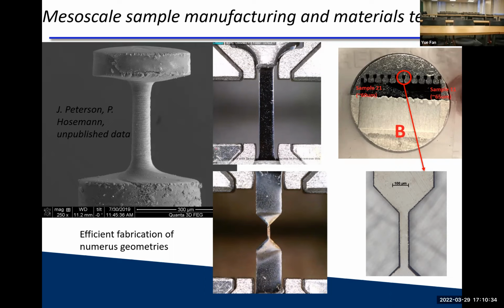What I haven't done yet, which I'm very eager to do, and we actually just made about a dozen of those, is test them with EBSD on, so to speak, and tensile them, and watch the orientation change on the surface. And if it's round, in theory, at least you could do it from different angles, which when it's square, you have the corner that you only got one side. So you may have a little bit more there. But we are early in that stage, so I don't know, maybe there's some other reasons to do it round versus square. But it's cool that you can.